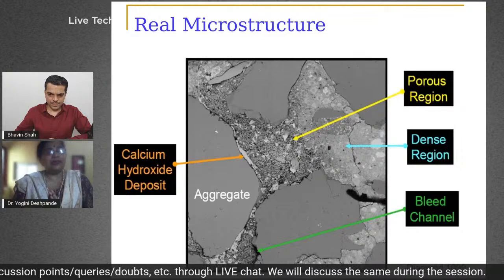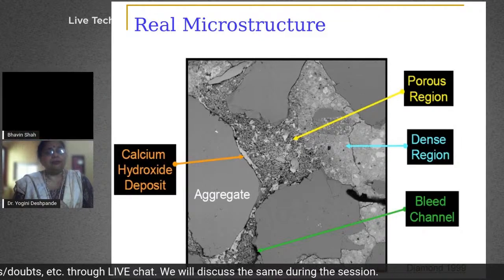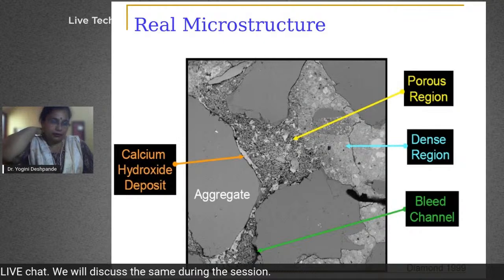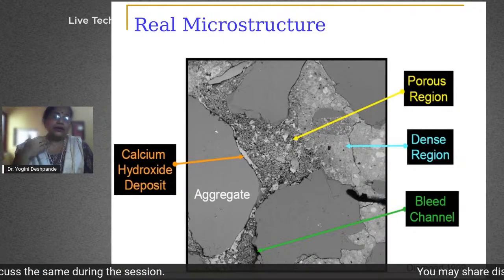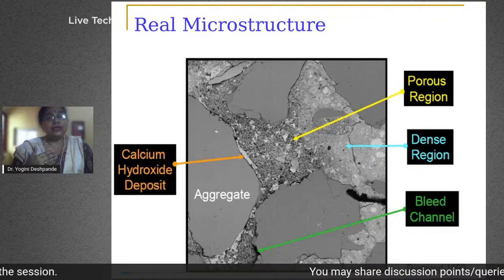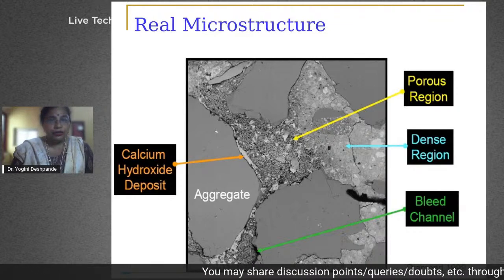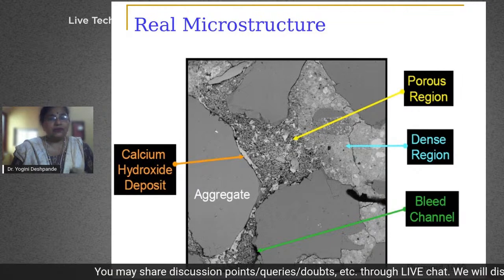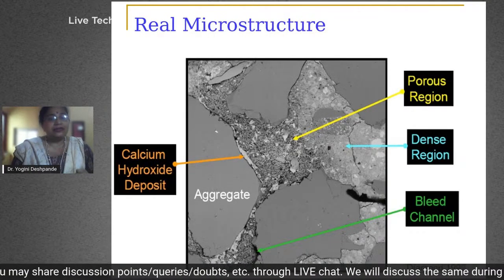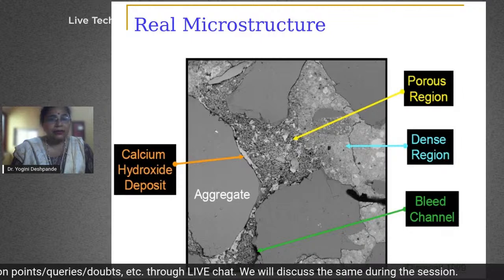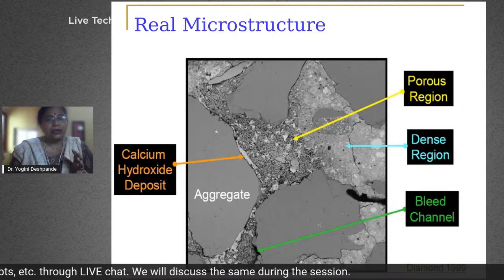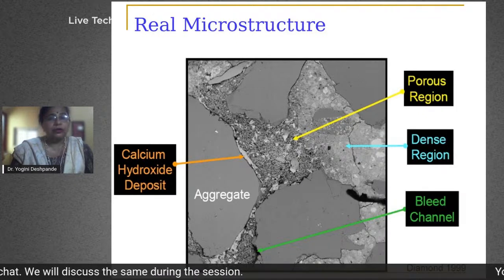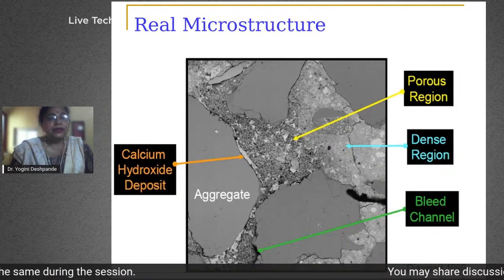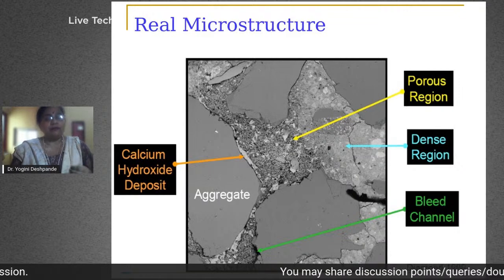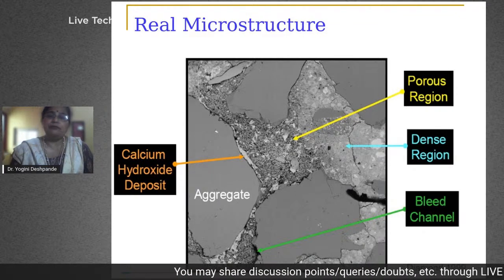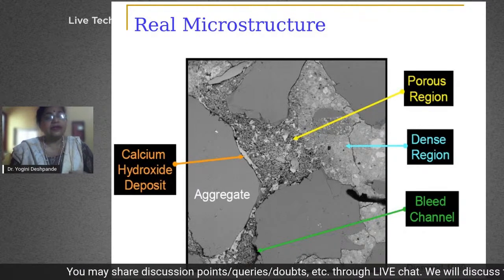Calcium silicate hydrate has a larger, tighter structure microscopically, and that is what ensures that the concrete will remain impermeable. The very solid gray area that you see is typically the calcium silicate hydrate. The mixture of black, gray, and white you see in this portion is typically a mix where you have calcium hydroxide being formed, along with some cement particles that have not hydrated.